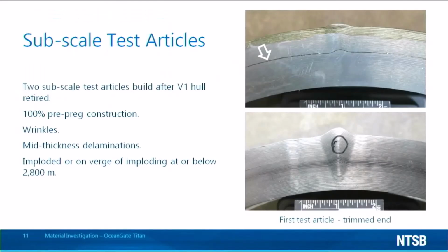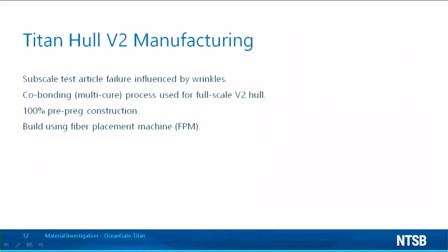The trimmed end piece contained two notable wrinkles and a mid-thickness delamination, as indicated by the arrow in the upper image. According to multiple former directors of engineering for OceanGate, both subscale test articles imploded or were on the verge of imploding at or below 2,800 meters. OceanGate identified these wrinkles as a likely cause of the low implosion pressure.